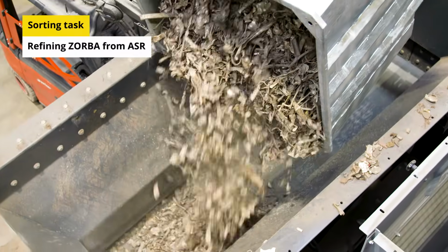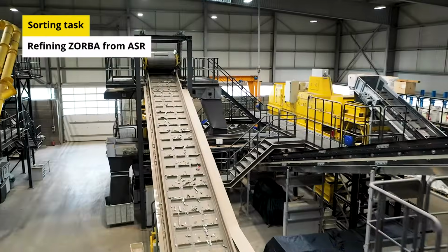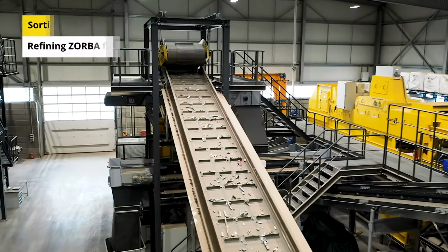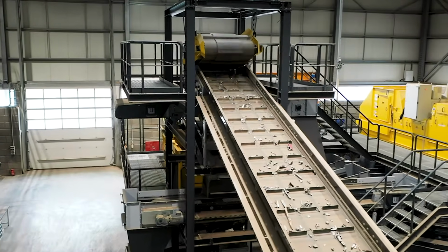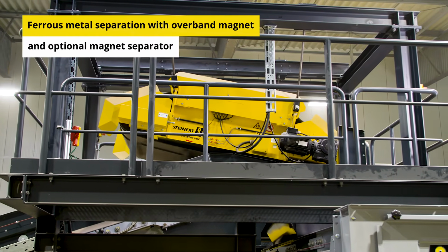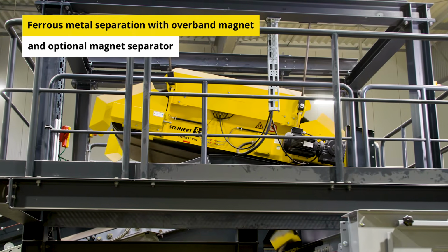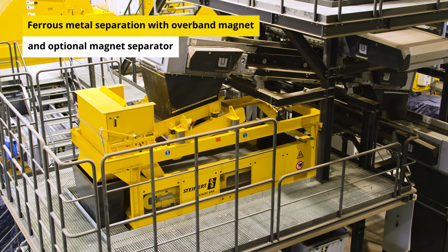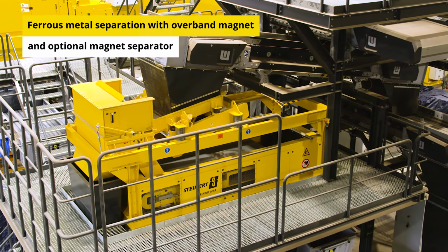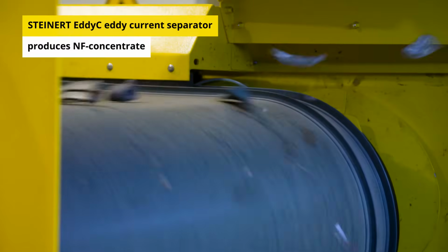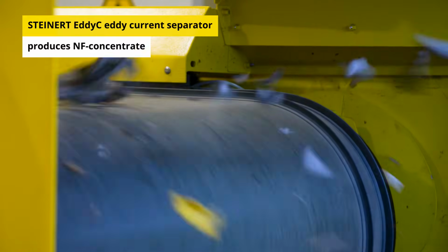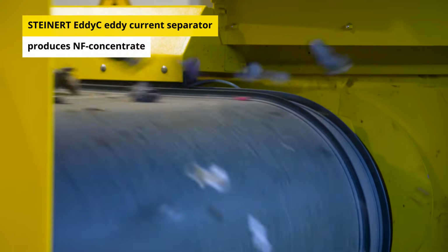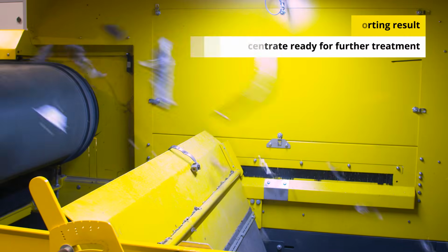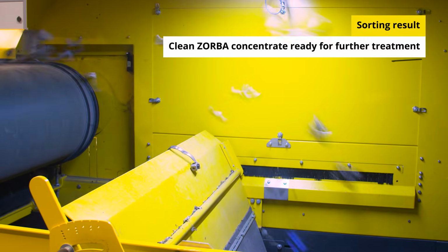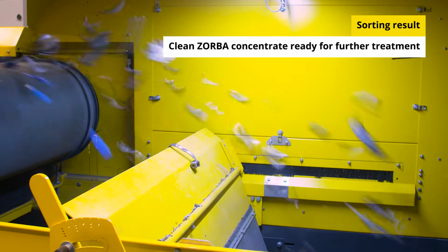For refining ZORBA from auto-shredder residues, we start with magnetic separators to recover ferrous and other magnetizable materials using either an overbelt suspension magnet type STEINERT UME or our double-stage magnetic separator STEINERT MRB. The remaining material is passed over an eddy current separator to remove non-metallic pieces such as plastic, wood or stones in order to create a cleaned concentrate of non-ferrous metals for further upgrading.